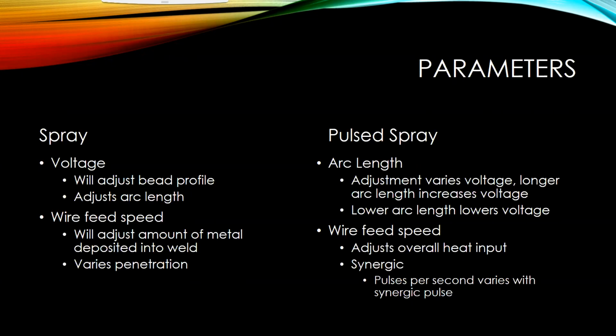For wire feed speed, that's going to adjust our overall heat input. Also, when we're running pulse, it's going to be synergic. What that means is after we've dialed in that arc length to what we want it to be, and we start adjusting our wire feed speed, it's going to maintain that arc length no matter what wire feed speed we use. So it'll transition smoothly. When we are adjusting our wire feed speed, though, it is also going to adjust a number of other parameters, which we're going to get into in just a minute.